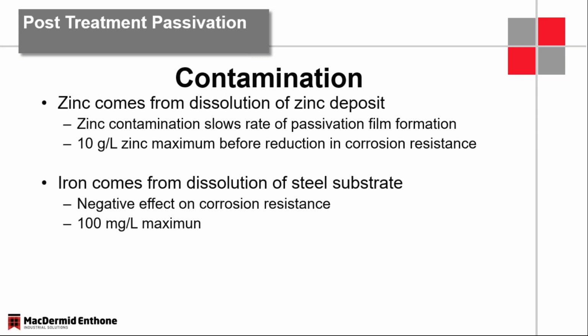Iron is even more important. You can only see 100 milligrams per liter on that. Parts in the bottom of the tank, boy, will that get some iron up there quickly because the zinc will strip away. Tubular goods have bare steel on the inside. Cast iron has porosity. Even using powdered metal. So iron is a big problem, and it can also change the appearance and make blue passivates and clear passivates look more yellow.